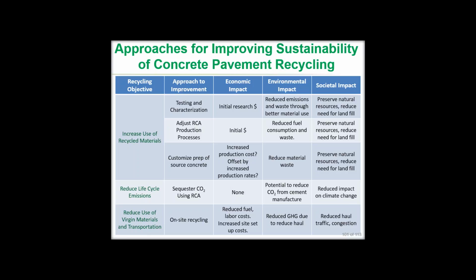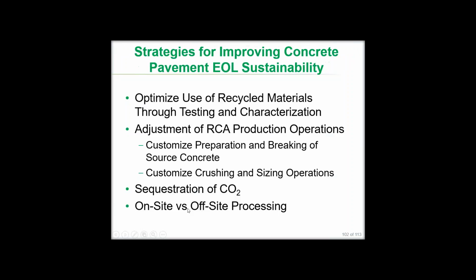Reducing the life cycle emissions. Using RCA as an approach for sequestering carbon dioxide is the one thing that came up there, particularly with the finer aggregate materials as the fines are produced, spreading them out and allowing them to recapture some of the CO2 which is driven off during the cement production process, because that's basically what you're recovering there. And then reducing the use of virgin materials and transportation through on-site recycling. And again, all the benefits environmentally, economically, and societally are summarized on this table.